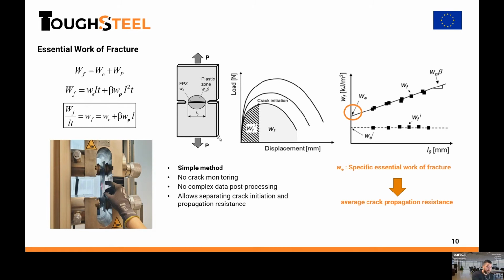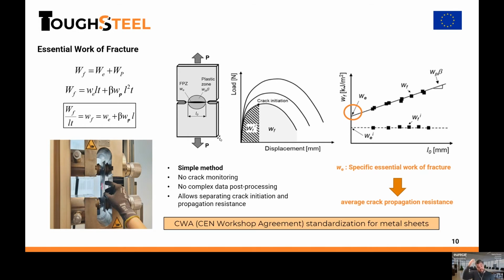So by making an average of these values, we can obtain this toughness at initiation, the essential work of fracture at initiation. Also, an important thing to mention here is that there is not yet a standard method developed to measure the essential work of fracture in thin metallic sheet. There is a testing protocol developed by the European Structural Integrity Society, the ESIS group, which was developed to measure the fracture toughness of polymer films, so of polymers. Then there are no recommendations regarding specimen preparation and so on for metallic materials.